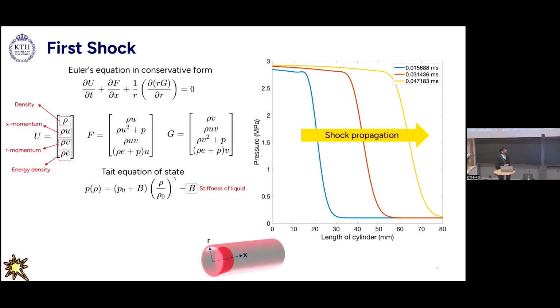So with all of that in mind, when we tried to plot the shock wave graphs, we understood that the shock wave we are getting is traveling inside a pressure chamber in a very small amount of time. If you look at the time steps mentioned on the top, that's roughly 0.05 milliseconds. If you think about this as a shock wave of, let's say, 1 Mach number, that roughly translates to 1,500 meters per second inside water. To cover the 8 centimeter distance of the experimental chamber, it takes roughly that time, 0.05 milliseconds.